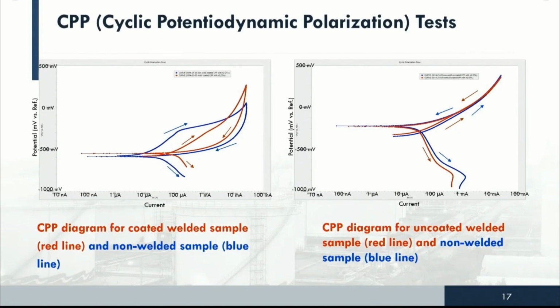However, for the welded and coated ones, we didn't get this increase, and the shape is different, and this indicates there is a partial passivation. There is the passive layer, or the first layer has been compromised. This is all I want to tell you, although from here you can also determine the corrosion rate, and we have observed that the welded, coated one has tenfold higher corrosion rate than the non-welded coated sample, which is in agreement with our linear polarization test before.